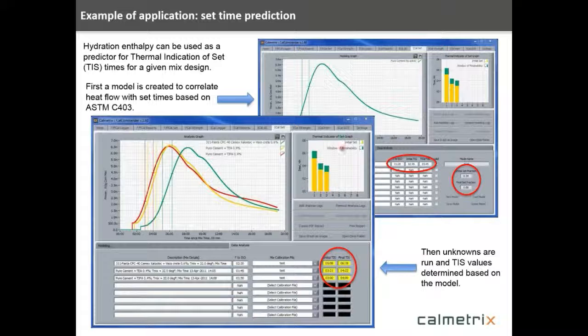Then you have a nice graphic up here in the software that provides a graphical indication of the initial set and your window of finishability in terms of comparing the different samples. So that's another great example of how you can use the calorimeter data in order to do some predictions. And again, as I mentioned for the strength prediction, this will not necessarily replace the use of your ASTM technique for developing the set times, but it's a great way to augment that and open up a much larger test matrix that you could not do otherwise.